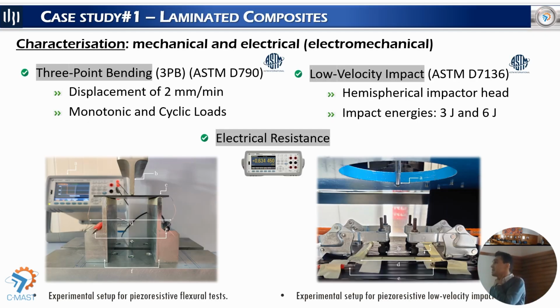In the first case study, we perform mechanical characterization of the samples, the typical and standard 3-point bending tests. We did cyclical tests and also monotonic tests till the rupture of the samples. And we also performed studies of low velocity impact to understand how our structures behave in this kind of impact occurrence. As I said, it is a real concern in the application of these structures. During the tests, we monitor the electrical resistance with a digital multimeter.